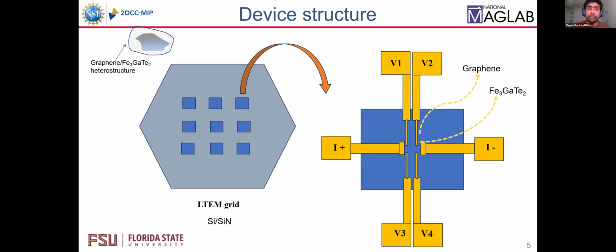So we are interested in making a stack of graphene and Fe3GaTe2. Fe3GaTe2 is very air sensitive, so we have to cap this material with graphene to protect it from air. In this particular project, we are interested in making electrical contact to this TEM grid and transferring our graphene-FGT stack on top of these contacts. So that was the main motivation.